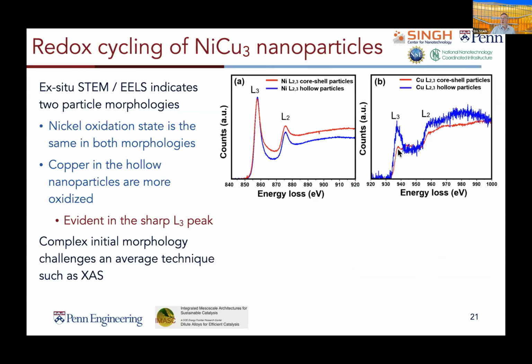But if you look at the copper in the hollow particles, there's a different near edge structure that's again consistent with it being a more oxidized structure, closer to the CuO oxide. And that's again evident in the presence of the sharp peak. Whereas if you have a more metallic structure, that L3 peak is reduced.